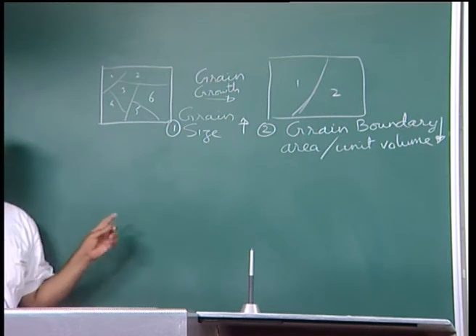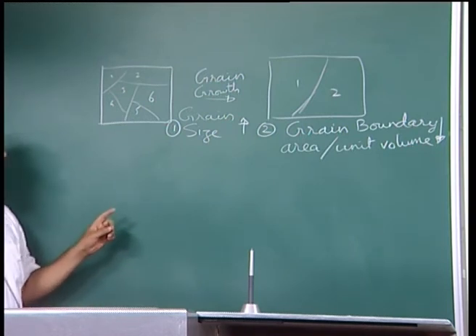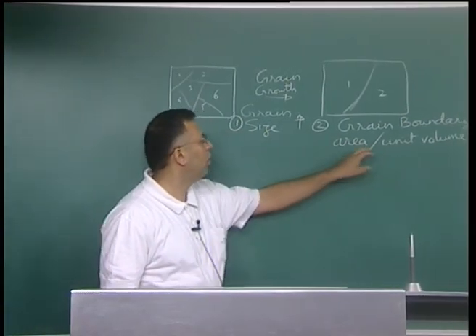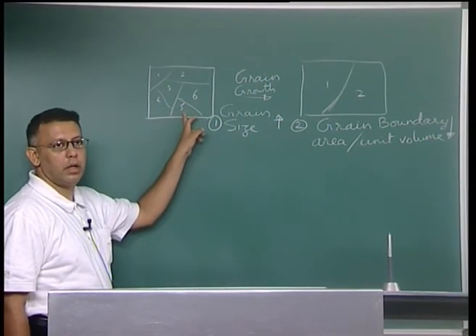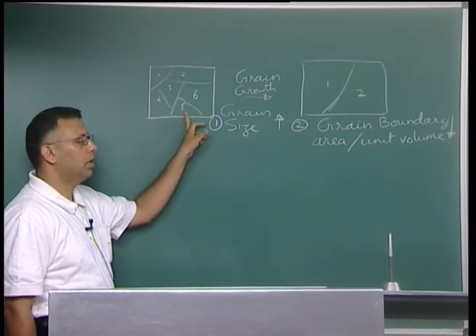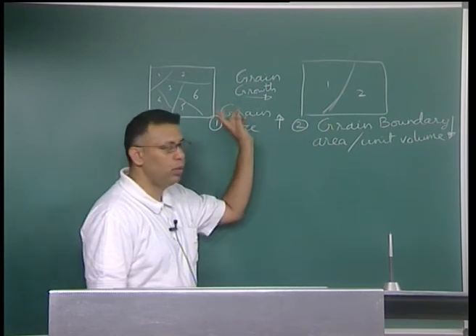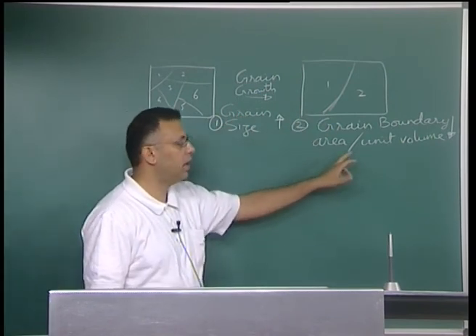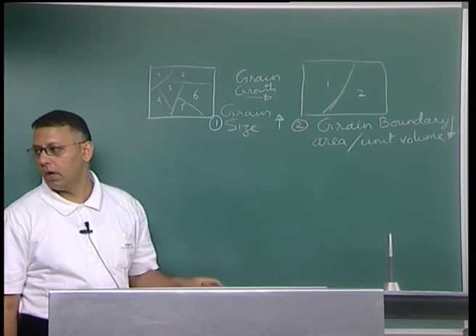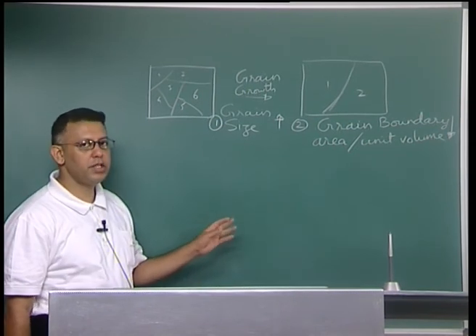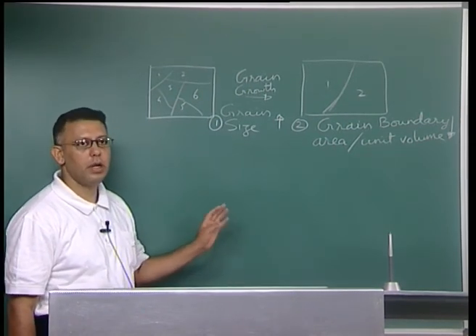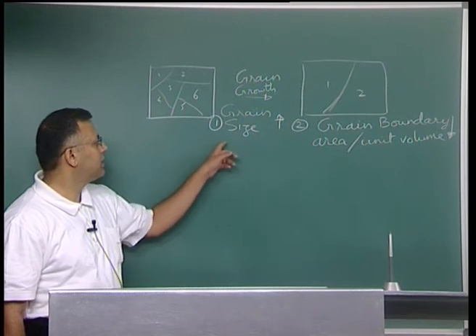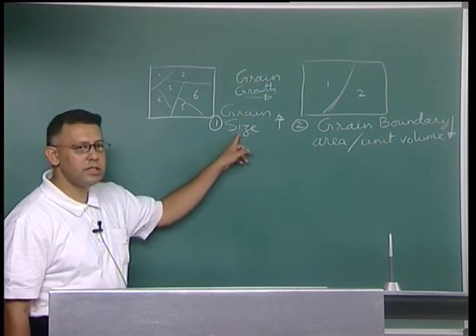So, what is the driving force for this? The driving force is the fact that the grain boundary area per unit volume in a fine grain structure is more as compared to this. That means during grain growth, my grain boundary area per unit volume decreases, which means my energy associated with the grain boundaries decreases. This is happening by an increase in grain size.